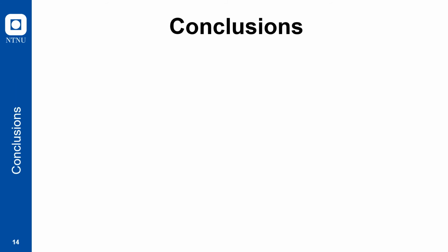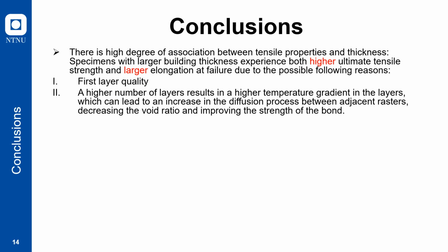And from that, we can get some conclusions. First, there is a high degree of association between the tensile property and thickness. So in detail, specimens with larger building thickness experience both higher tensile strength and larger elongation at failure, due to possible reasons. First, first layer quality, because for 3D printing, especially FDM, the first layer is really important to print and optimize, and sometimes it can be affected by many other factors. So there's uncertainty in first layer quality.